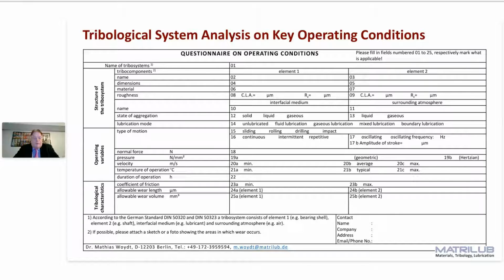the operating conditions of your application, the contact stress. Do we talk about a geometric contact stress or about a Hertzian contact stress? The velocity, sliding speed, mean, max, average, the same for temperature, duration, and so on. And you see, you generate here a quite big matrix of test conditions. That's why you also have this wide range of wear and friction. But if you want to have results which can be transferable to an application, you should have, as best as possible, the same conditions, including the materials, in your tribological test equipment.